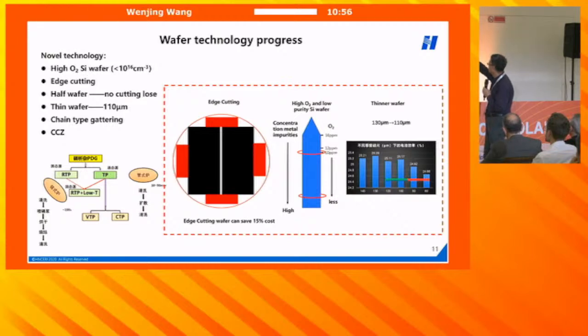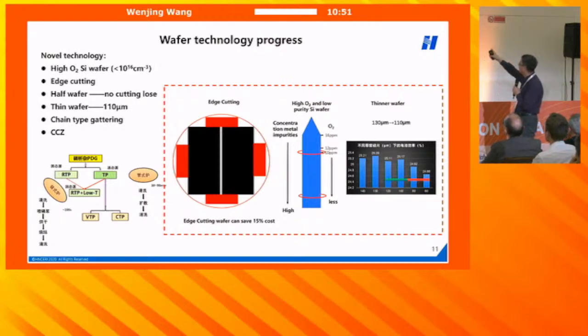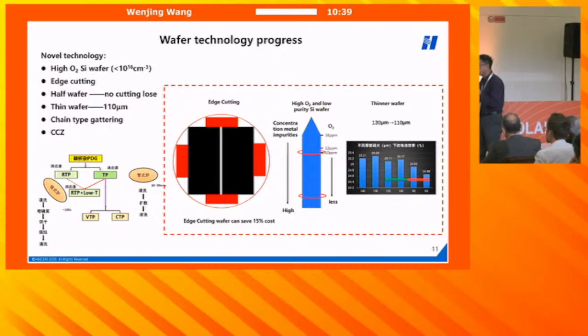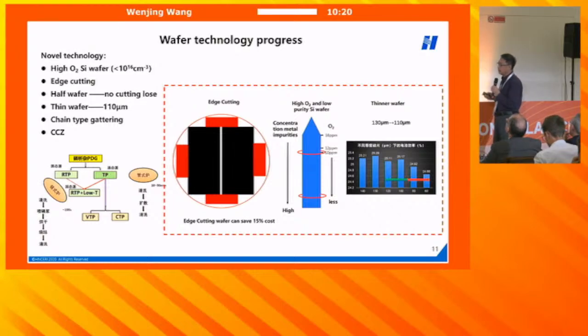For this figure in the middle, in the top area of the ingot, the oxygen density is high. It cannot be used for TOPCon because the TOPCon process temperature can reach 1050 degrees centigrade, so it will have OSF rings. But our HJT cell is only low temperature, below 200 degrees centigrade. So we can use that high oxygen density wafer, which will be cheaper.